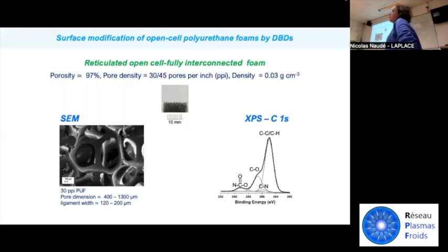For our work, since it was really a proof of concept study, we decided to select an open cell polyurethane foam with a porosity of 97%. And as you can appreciate from the SEM image on the left, this foam is really characterized by an isotropic, fully interconnected network of ligaments and pores. So this was really a choice to select this kind of material to start our work. On the right, the typical carbon 1s XPS signal of the foam is reported. There is a main contribution from the hydrocarbon component, and then some contribution from oxygen and nitrogen containing functionalities.